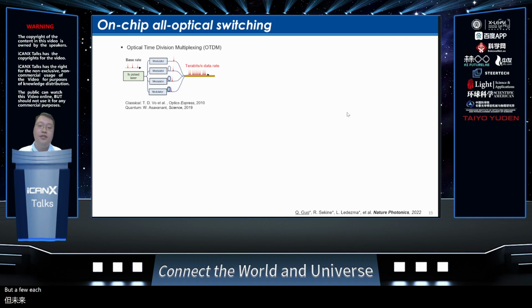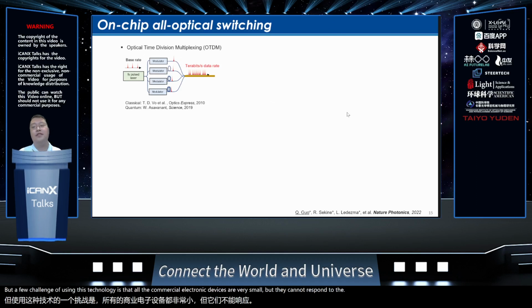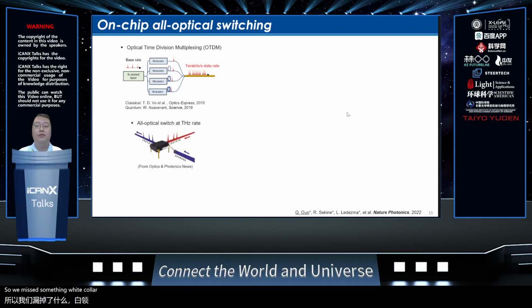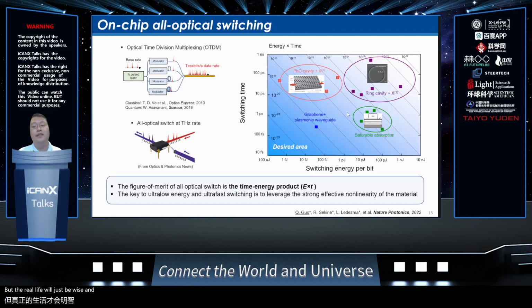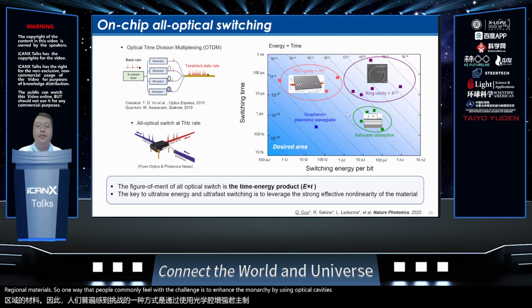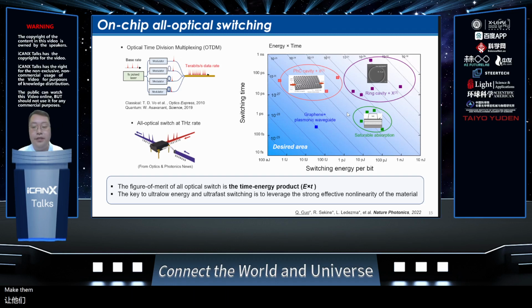But the key challenge of using this technology is that conventional electronic devices are very slow, so they cannot respond to such a high data rate. So we need a device called an optical switch to process information at terahertz data rates. But realizing this device in a solid state platform is very challenging because the optical nonlinearity is usually very weak in conventional materials. One way that people commonly deal with this challenge is to enhance the nonlinearity by using optical cavities. But this approach makes the nonlinearity very slow because we dramatically increase the photon storage time in the cavity. Another approach is to leverage the intrinsic material nonlinearity, such as absorption, but this requires a much higher input pulse energy.